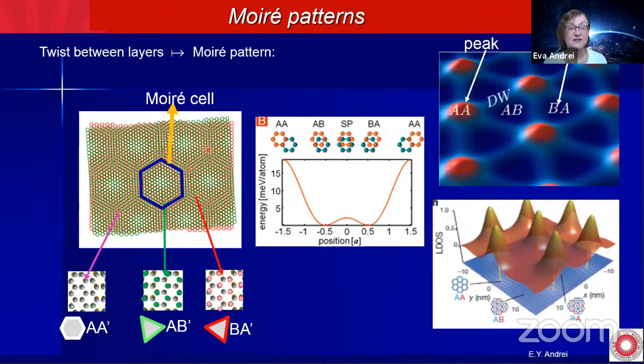So when the angle is very small, the lattice is distorted in such a way as to almost completely squeeze out the AA region, and it's mostly AB or BA. And this is a saddle point in between. So the AA regions, because they're energetically unfavorable, they actually stick out of the plane. And this is what we see in scanning tunneling microscopy. The density of states also actually has peaks in the AA region.